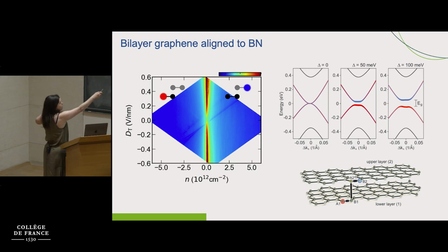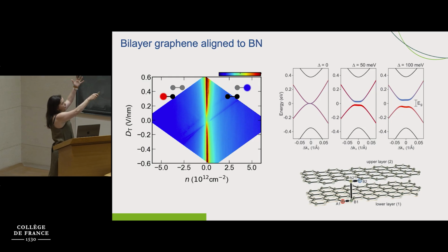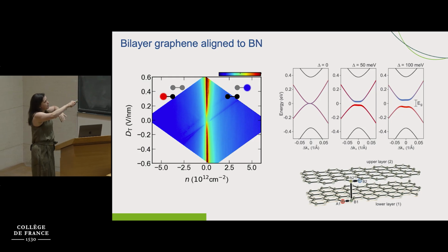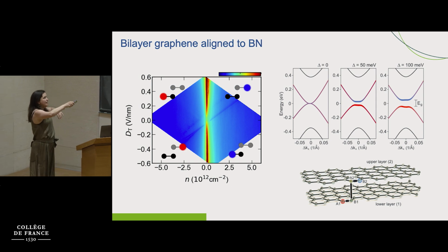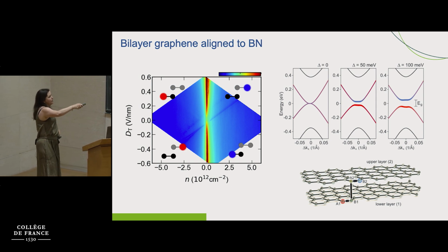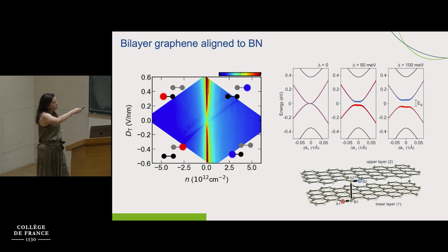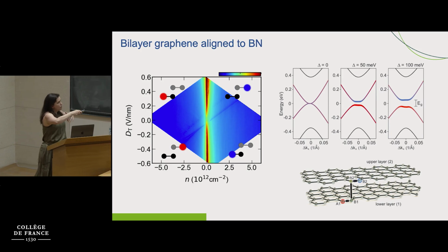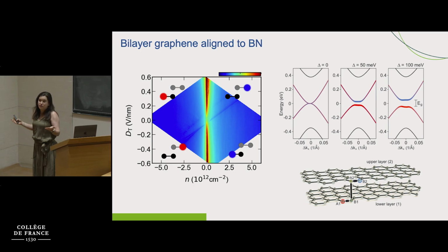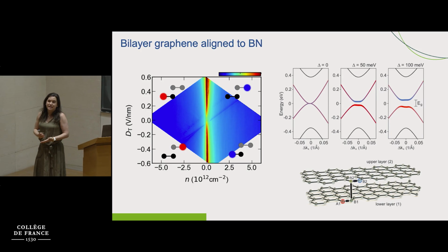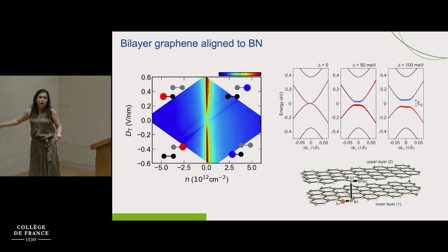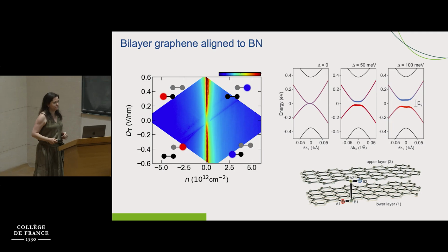It means that when we have a positive displacement field, we're going to be pushing the electrons towards the top layer or the holes towards the bottom layer. And the same is going to happen for a negative displacement field. I'm going to be pushing either the holes towards the up layer or to the bottom layer. And this is going to be very important because then it means that I can put my electrons closer to the Moiré lattice or farther from the Moiré lattice.